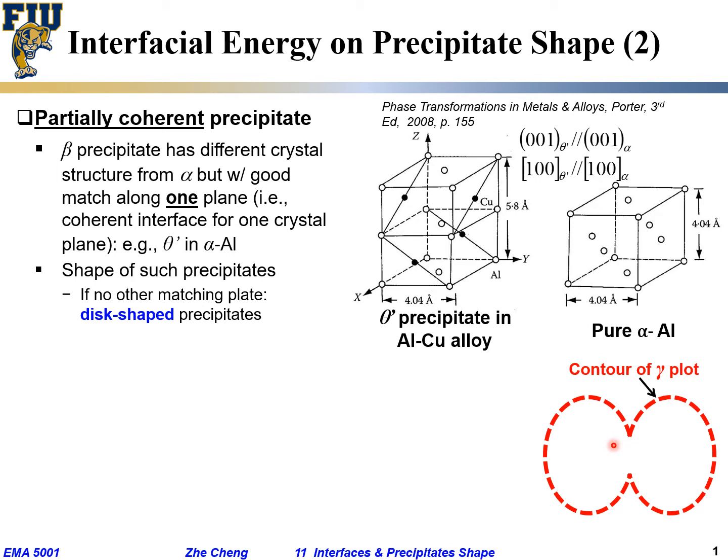But then when we said, okay, once you have the so-called gamma contour plot, you can get the so-called equilibrium shape of a crystal by so-called Wulff construction. And what is Wulff construction? It's kind of like from the center to any point on this contour plot, and then you draw not a tangent, a perpendicular plane, and the inside cut of all those planes will define this blue shape, which is our equilibrium shape. From the center to this point, you draw a perpendicular plane.